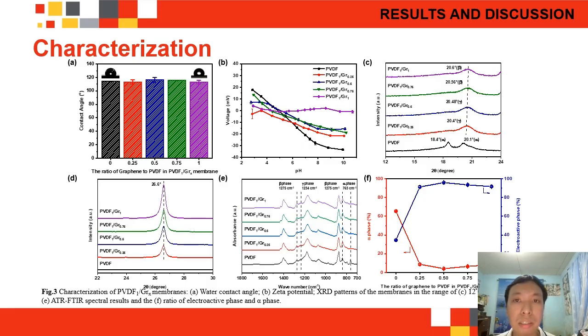Next, figure C. XRD analysis reveals that the PVDF membrane initially shows alpha phase peaks at 18.4 degrees and 20.1 degrees, corresponding to 020 and 110 planes. Upon adding graphene, the crystalline structure transitions. The peaks shift to 20.3 degrees to 20.4 degrees for gamma phase, while they shift to 20.5 to 20.6 degrees for beta phase. Also, from figure D, a new diffraction peak at 26.6 degrees appears and increases with graphene content, indicating that graphene interactions induce the piezoelectric beta phase, which is crucial for catalytic performance.